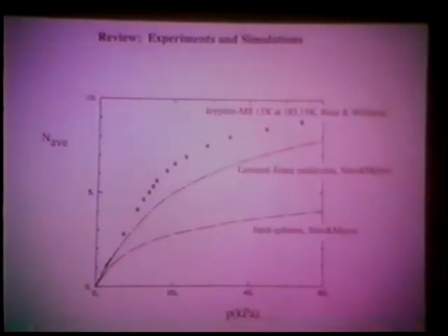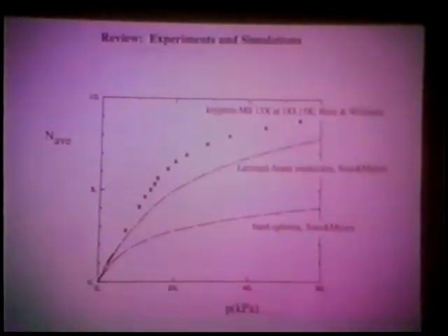And then, to account for the gas-gas interaction, they performed Monte Carlo simulations of the gas molecules inside the cavity. Now, they did two kinds of simulations. One where the molecules saw each other as hard spheres, and another where they saw each other as Lennard-Jones particles. Let me emphasize that the hard sphere molecules still interacted with the walls of the cavity through the dispersion and electrostatic forces, but they saw each other as hard spheres. And then they added on the Lennard-Jones interaction, using parameters from gas phase modeling of the krypton molecule.